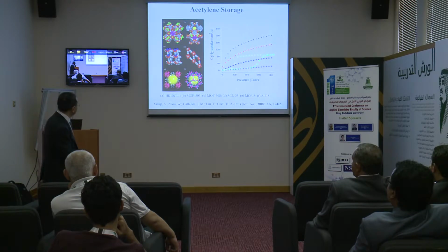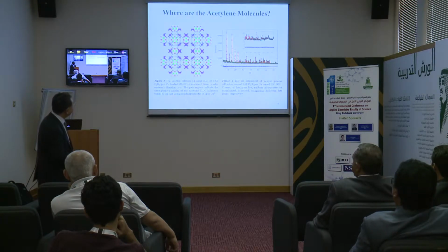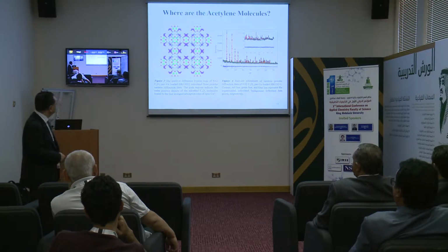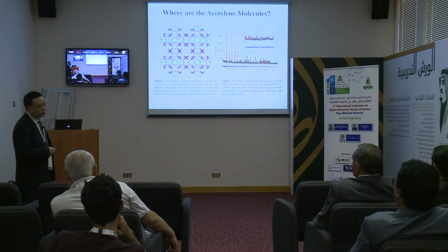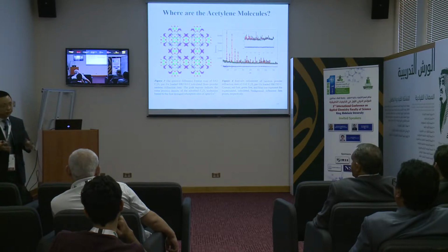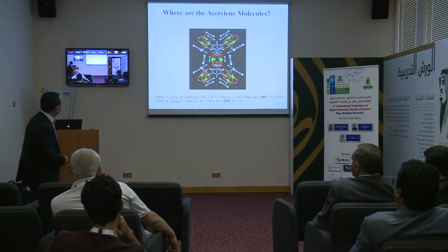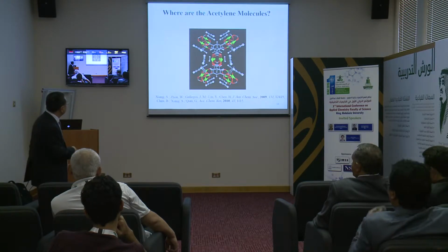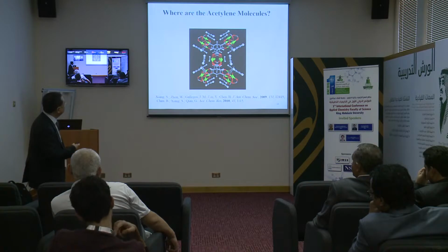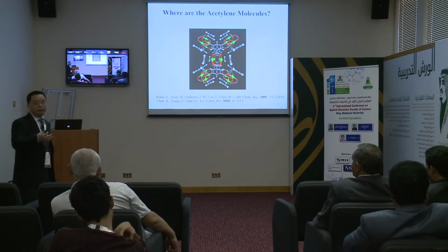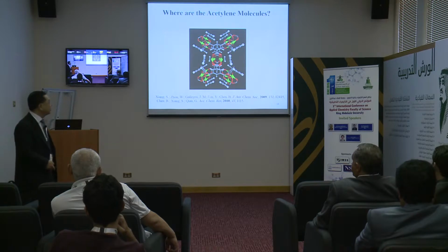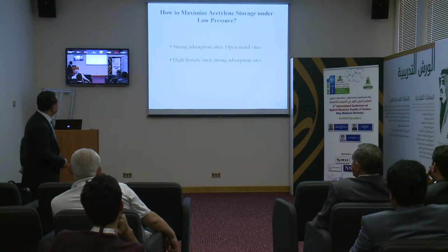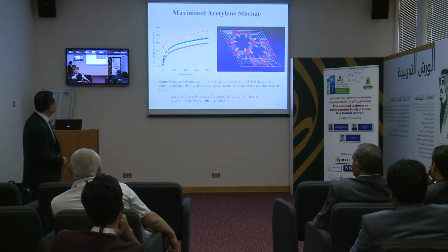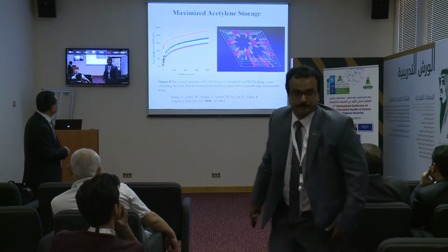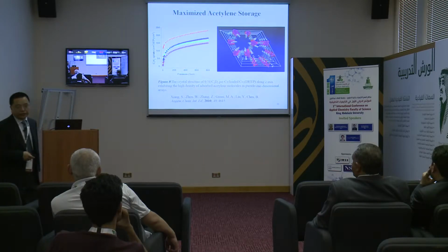This is the record one. And furthermore, we even established the binding site by neutron diffraction studies, clearly indicating this open metal site binds with acetylene. Although the binding is still not a chemical binding, it is a kind of strong Coulombic interaction. So this is very clear. So now we can further enhance the acetylene uptake by immobilizing more open metal sites and a little bit stronger interaction. So we realized that this MOF-74 series is very suitable for acetylene storage. So we have another record acetylene storage material.